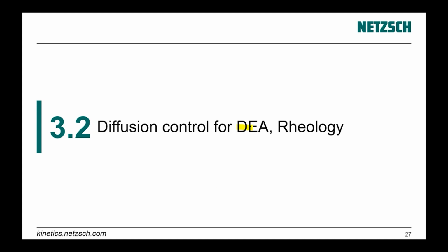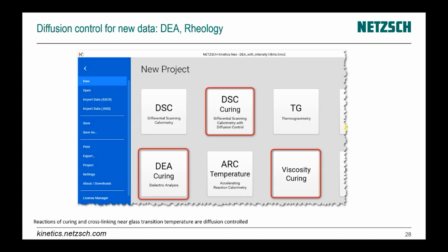And now a next example is not about the second parameter, but here we have a diffusion control for DEA and Rheology. Up to now, we have the curing. We can make analysis for curing reactions only for DSC. And from version 3.0, we have a possibility to make analysis of curing reaction with diffusion control, also for DEA and for the viscosity.